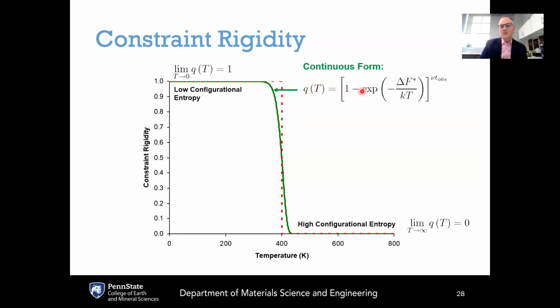This can be described in continuous form as shown here, where the constraint onset function q(T) is basically described by this Boltzmann distribution, 1 minus the Boltzmann distribution. So this is the probability now of being confined instead of the probability of escaping. And this is the probability of remaining confined over some observation time t_observed. This tends to be a relatively sharp function, which means that we could approximate this continuous function as a unit step function. This theta is a unit step function here, where it is 1 at all temperatures below this onset temperature T_q, and then it's equal to 0 at all temperatures that are above the constraint onset temperature T_q.